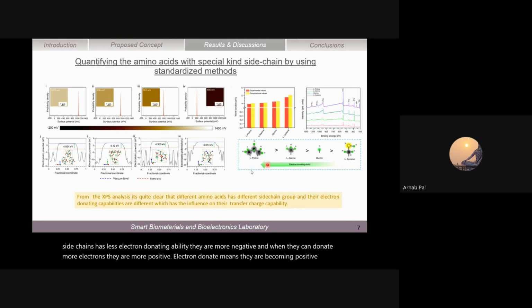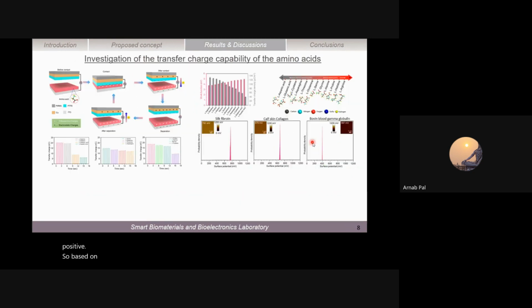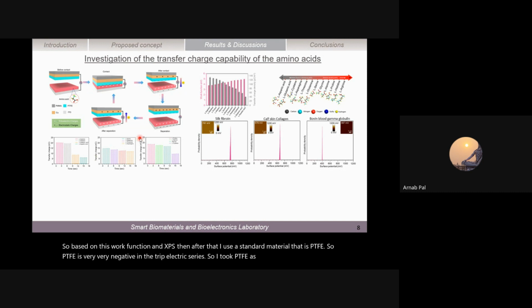So based on this work function and XPS, after that I used a standard material, that is PTFE. PTFE is very, very negative in the triboelectric series, so I took PTFE as a standard material. Then I used the amino acid layers, different amino acids, as the counter layer, and I did the contact electrification. Here you can see the output values for contact electrification, and then I calculated the transfer charge capability, like when they are transferring the charge, when different amino acids come into contact with the PTFE layer.